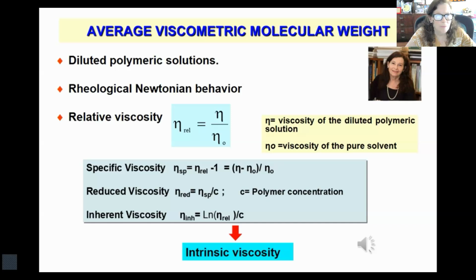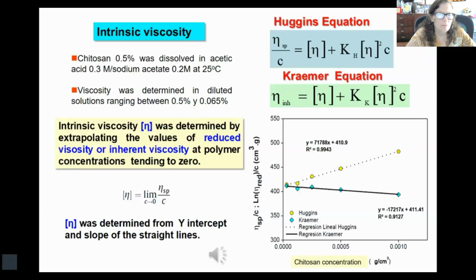The average viscometric molecular weight was obtained from the intrinsic viscosity. We work with diluted polymeric solution having rheological Newtonian behavior and measure the relative viscosity, that is, the viscosity of the diluted polymeric solution divided by the viscosity of the pure solvent. From this value, we calculated the specific, reduced, and inherent viscosity.